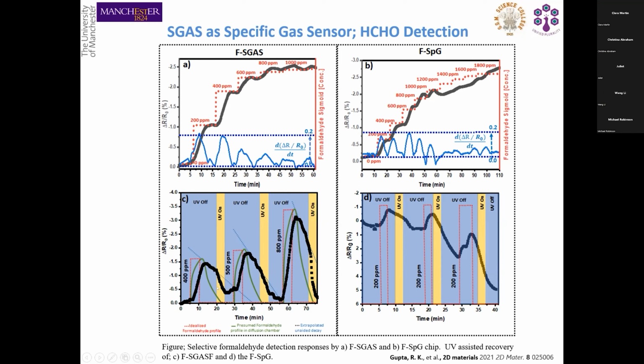What happens is that this UV affects the bond between the TFQ molecules and formaldehyde, rather than breaking the TFQ from the graphene, where they are anchored to detect the formaldehyde selectively. At the same concentration, the sensor recovers as soon as the UV light is switched on. If we do not expose it, the sensor starts recovering, but the recovery is very, very slow. Through the blue line, it would have recovered like this, but when you illuminate it with the UV, the recovery becomes faster.